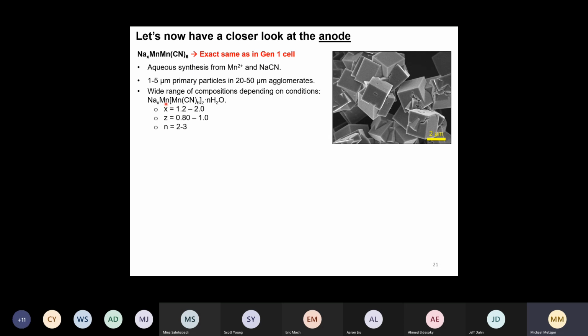Then we have a manganese coordinated to the nitrogen, another manganese coordinated to the carbon. And this X is, again, this stoichiometry factor by which the two manganese differ. So if it's 1, then they are exactly the same, but it can also be a little deficient in this hexacyano group manganese. And then we fill this up with either, well, we would fill it up with coordinated water, but this N can also be larger than just what comes from the coordinated water, because we always can have in these materials this zeolitic water.